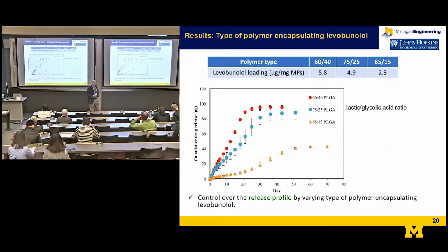So you have tremendous flexibility in regulating how much of each drug is released as a function of time. And this illustrates this flexibility here in the case of the microparticles. These are PLGA, so you can regulate the ratio of the lactic to glycolic acid in this polymer, and that has a big effect on its hydrophobicity, and you can see the strong effect on the release rate here that you get by controlling that.